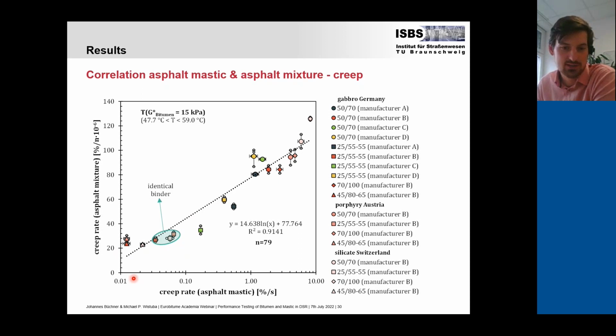They have very low creep rates in the DSR, while they also have low creep rates in the mixture, but here they are quite zero, almost zero, so to say, compared to the unmodified binders, which are here on the top, and especially the soft binders here. The 70/100 is here in the very corner, but also the 50/70 is here in the top. You see they have a creep rate in the range of 5 to 10% per second, and this corresponds very well with the high creep rates this material induced in the asphalt mixture.